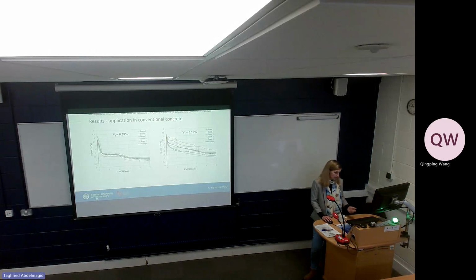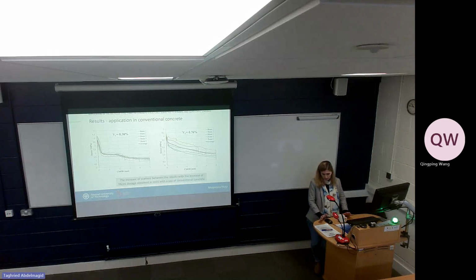So these are the examples from our research with concrete. So we get almost no scatters for the very low amount of fibers. But when the amount was higher, the scatters were much bigger. So this is also a huge disadvantage, because of course we have some safety factors, but you can see that this difference is quite big. So for sure, I will say that we shouldn't use it in concrete. In self-compacted concrete it is great, but in concrete it's not recommended.